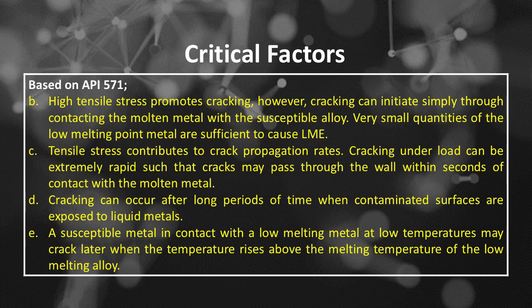Number C, tensile stress contributes to crack propagation rates. Cracking under load can be extremely rapid such that cracks may pass through the wall within seconds of contact with the molten metal. Number D, cracking can occur after long periods of time when contaminated surfaces are exposed to liquid metals. Number E, a susceptible metal in contact with a low melting metal at low temperatures may crack later when the temperature rises above the melting temperature of the low melting alloy.